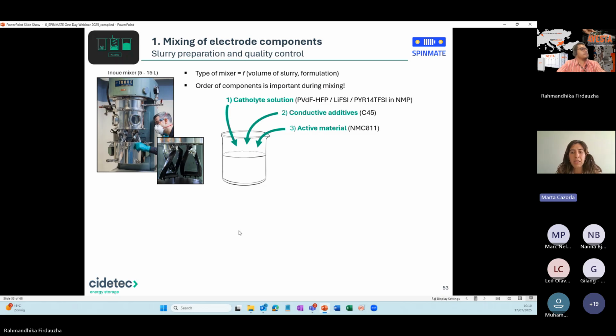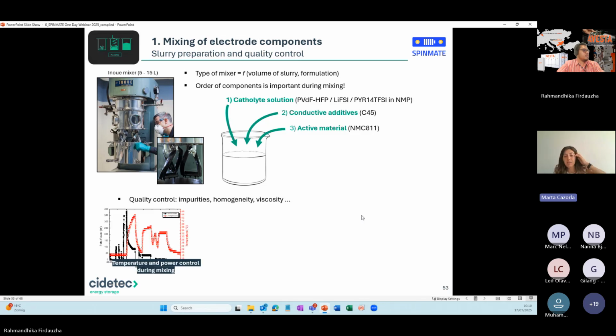So in a cathode, in a positive electrode, we first start preparing the catholyte solution. And then we add the conductive additives and the active material. There's some resting time between components, and all this mixing is done at a certain speed. And for quality control, it's very important to measure the temperature and the power during the mixing.